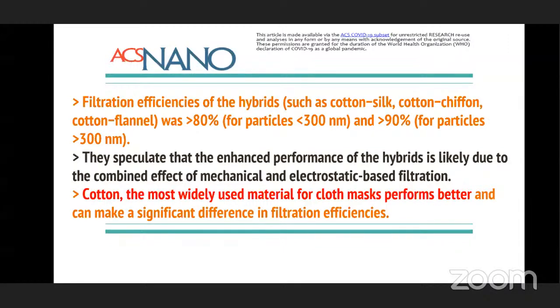They speculate that the enhanced performance of the hybrid is likely due to the combined effect of mechanical and electrostatic based filtration. So as I discussed earlier, they have proposed that the filtration efficiency is due to this combined effect of the mechanical and electrostatic based filtration due to the hybrid composition. Cotton, the most widely used material for cloth masks, performs better and can make a significant difference in filtration efficiency. So I want to highlight that there is no need to use a silver or a gold mask for protection. A simple cotton fabric mask is sufficient.